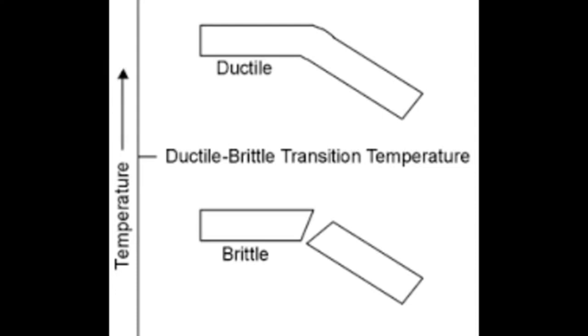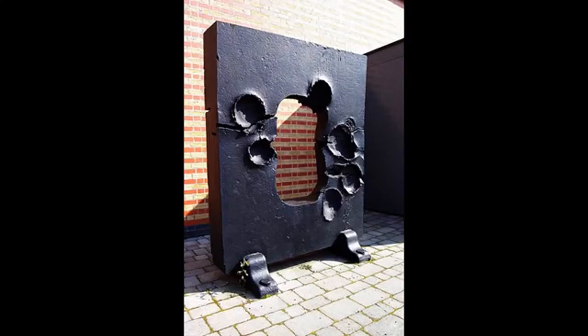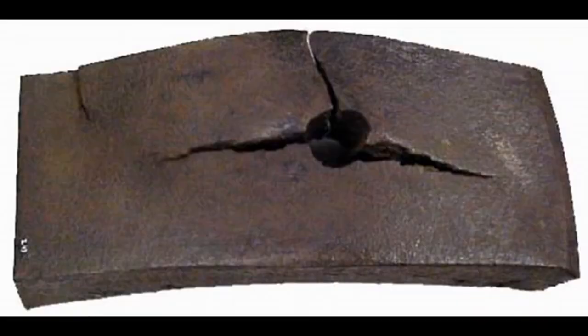Above this, you get ductile failure, that's to the right of the line, and this involves the material splitting and bending. Again, to use an extreme example, this is an effect a bit more like poking a hole in a sheet of cardboard with a pencil or stabbing into a plastic drinks bottle. Now, the early tests of cannon against iron had seen the latter ductile behaviour. Now, reports were coming in of the brittle type of failure. But the material being used on the ships was not that much removed from the material that had been used in the test. So what was the problem?